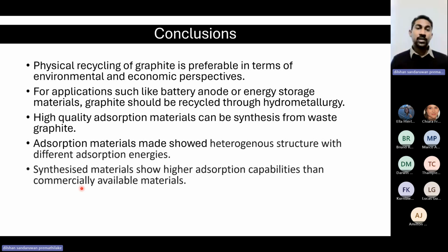And also, during the second experiment, we identified that high quality adsorption materials can be produced from the waste graphite. It's a good candidate for this purpose. This is mainly because of the increased interlayer spacing between the graphite layers that happened during the continuous charge and discharge cycles. And also the adsorption materials show a heterogeneous structure with different adsorption energies. This is why it followed the Freundlich isotherm model.